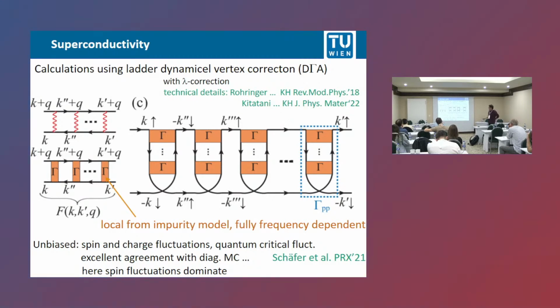Now these spin fluctuations act... we also treat charge fluctuations on an equal footing, but we find here predominant antiferromagnetic spin fluctuations, and these spin fluctuations act as a pairing glue between two electrons in the Cooper channel. In this way, they give rise to superconductivity. So the method is not biased. We can get S or P or D wave superconductivity, but for this calculation here, we get D wave superconductivity mediated by antiferromagnetic spin fluctuations.